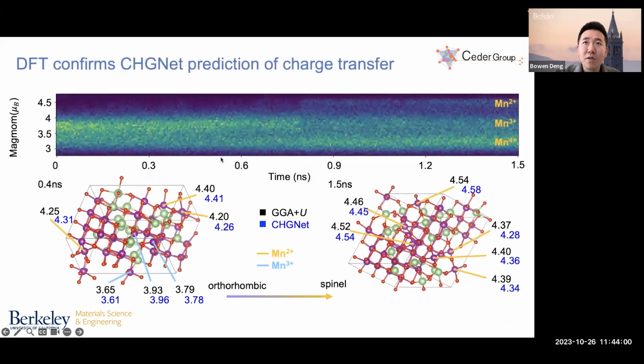And to validate our observation with CHGNet, we sent the structures at 0.4 nanosecond and 1.5 nanosecond of the CHGNet MD to spin polarized DFT calculations. And the DFT results actually show a highly consistent distribution of this tetrahedral manganese 2 and 3 ions as compared to CHGNet long time MD. So DFT also rediscovers that in the early part of the simulation, we have both manganese 2 and 3 on the tetrahedral sites, while in the latter part of the simulations, most of these tetrahedral manganese ions become manganese 2+.